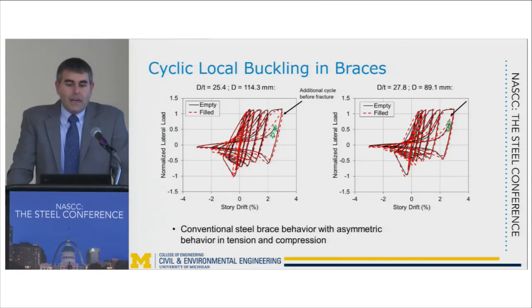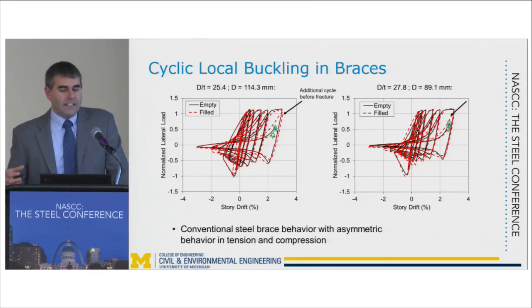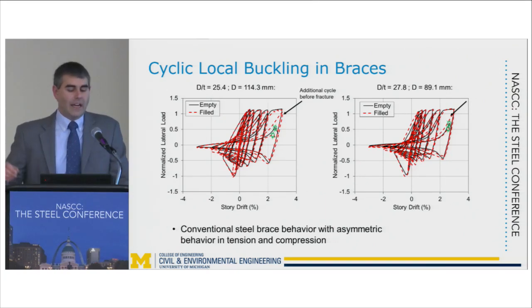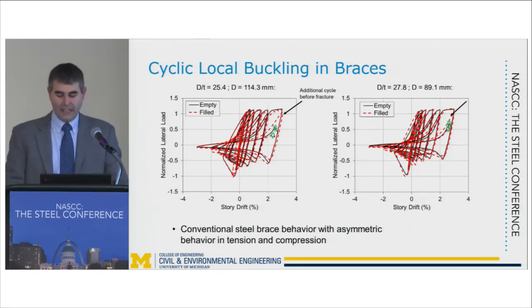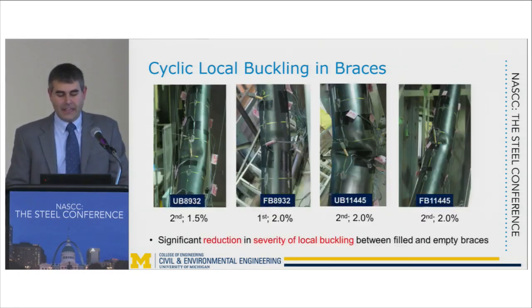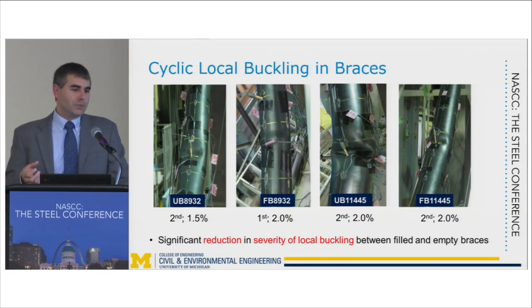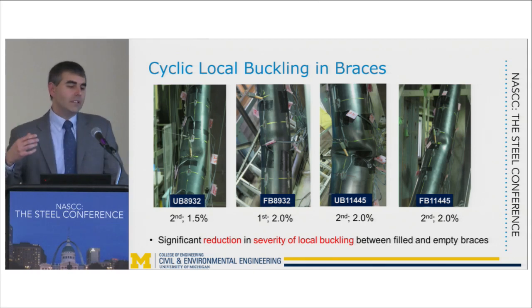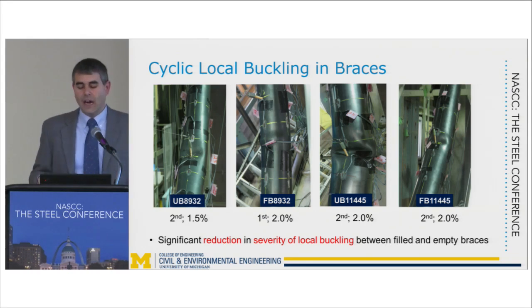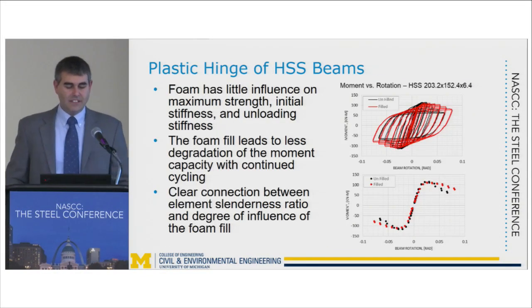So for the braces, what we found is that by having the foam fill in there, we're able to increase the ductility of the brace, and we're actually able to make it one or two more cycles before we see fracture in the brace because of the inhibiting of the local buckling where that foam fill is located. So you gain those advantages. We also see a severity of the local buckling decrease with continued cycling that you don't see with some empty braces. And it's well known that as HSS sections undergo local buckling and then we cycle those braces, right, we eventually get fracture. So if we can prolong when fracture occurs and potentially also increase the diameter thickness ratio that's allowable, then we can gain some significant benefits there.